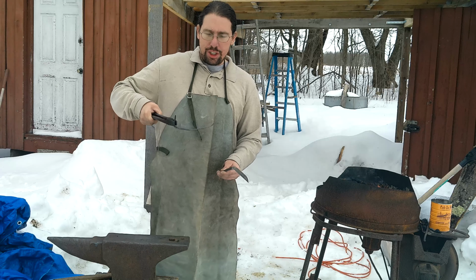Again, really small, really fine pieces that we're working with. You can overheat really, really quickly. Now, overheating, the tang is not going to be hardened. So if you get a little spark or two off the very end of the tip of your tang, most of that's going to get cut off anyway. I'm only going to leave about 3/8 inch to stick into the handle. And the tang's going to be about an inch, inch and a half long, you'll see hanging down over here. So most of that's going to get cut off. So that's not as big a deal as if you get crazing on the blade itself. But still, we don't want to needlessly cause ourselves problems.